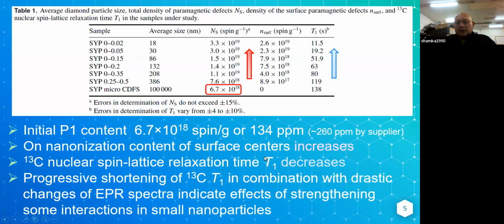C13 nuclear spin-lattice relaxation decreases, shortens. Why? Because of the increasing number of paramagnetic defects, which helps the faster relaxation. Progressive shortening of C13 relaxation in combination with drastic changes of EPR spectra indicates some effects of strengthening of interactions in small nanoparticles.